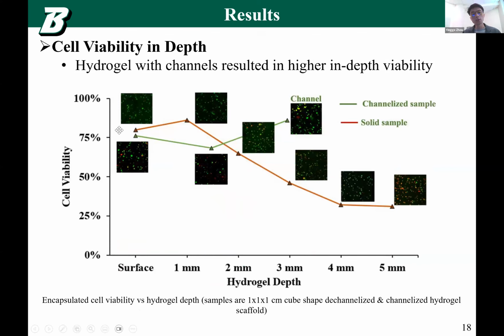channels. And this is the cell viability from the surface of the hydrogel all the way to the center of the hydrogel. For this sample with channel, we don't have the center 4 millimeter and 5 millimeter depths, because there is a channel at those depths. But we can see the green cells are more in the one with channels compared to the one without channels.